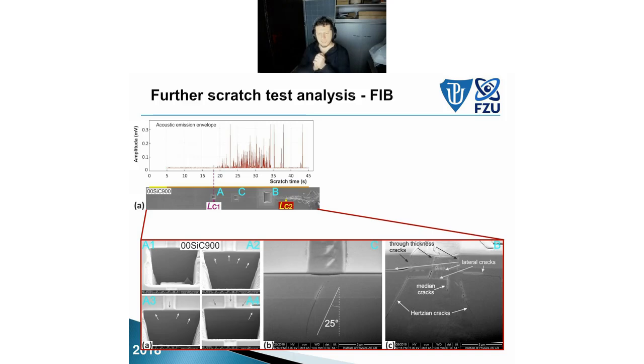So we used focused ion beam. We take out the material and check the cross section. Here in the cross section, we can see the coating and the substrate, a nicely adhesive system, no problem there. And in pure silicon carbide, we saw cracking occurred firstly on the surface. Sorry, it cannot be seen nicely, but there are semicircular cracks going from the surface into the depths, and some secondary cracking going from the substrate or from the interface.